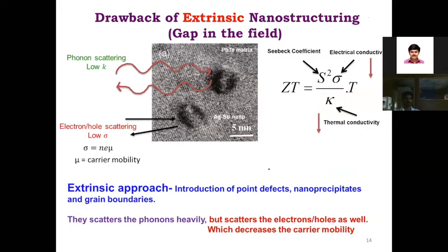There is a drawback in this extrinsic nanostructuring approach, because with time we have realized these nanostructures in a matrix can scatter phonons significantly. It will decrease thermal conductivity extremely well, but at the same time it will decrease the mobility because it will scatter at defects, dislocations and the boundary. It will scatter electrons and holes, so we will see a decrease in electrical conductivity as well. That means we are compromising with the numerator part of the ZT.